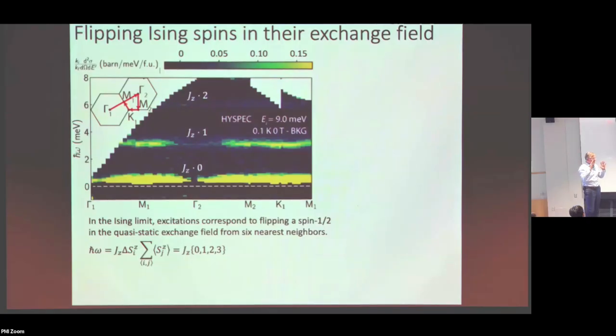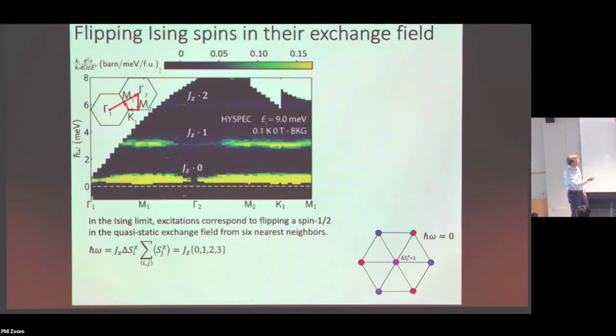We probably should have, but now we understand why this is a very natural thing to have in an Ising system. If I totally turn off the transverse part of the interaction, so I just have the ZZ term, then the excitation I'm doing is just flipping a spin in its exchange field. And its exchange field is set up by the 6 spins that surround it. If I have as many up as down spins, then the exchange field is actually 0, and it costs me no energy to flip this spin. That was my target spin to flip. And so that accounts for this low energy sector.